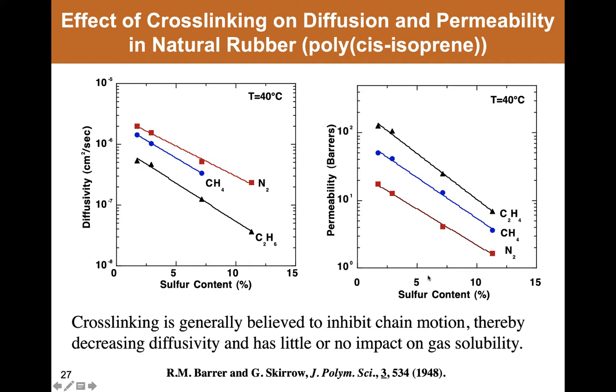If you remember and look back to the original Flory-Rehner paper describing the thermodynamics of solvent uptake in cross-linked polymers, Flory was concerned with exactly this problem when modeling the thermodynamics of rubber that had been cross-linked with sulfur. What Barrer and Skirrow found is that the permeability goes down significantly as the cross-linking density goes up, or as the sulfur content goes up. And this is largely due to a decrease in diffusion coefficients. There's little or no impact on gas solubility.